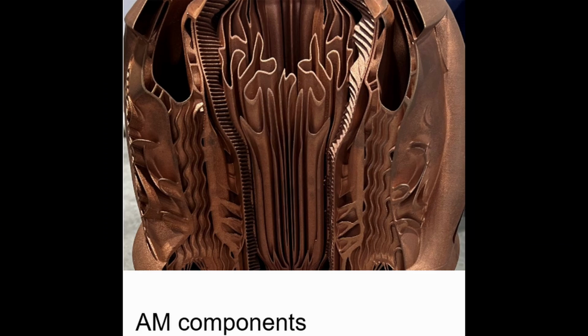And then the fourth one that we're mostly working with today, I would say, is doing the heat treatment inside the HIP. And this is where the AM discussion comes in, because we can shorten the supply chain basically for AM components by densifying an almost dense part, and improving the fatigue life of that part at the same time as doing the heat treatment and setting the microstructure. So that's kind of where we're acting today. But the powder metallurgy area is really growing, and that's an interesting one. That's good to know, coming out of the powder metallurgy family.